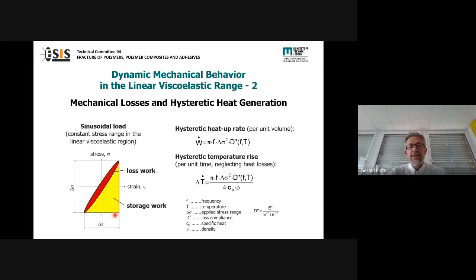And in many polymers, it is not possible to do the tests at very high frequencies, because if you increase the frequency... You see here the equation that describes the hysteretic heat up rate, and also here an equation for the hysteretic temperature rise. And you see here the temperature rise is dependent on the frequency. Specifically also on the stress range, the stress amplitude, even to the power of two, so it's even more important. And you see here material parameters, like the specific heat or the density of the material, but specifically also the